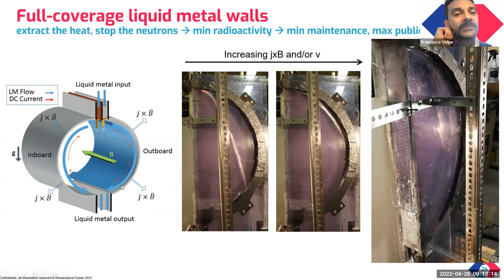So it's tens of kiloamps versus a few kiloamps. These are a rigid, very high current filament attracting a deformable current filament, but carrying a much lower current, orders of magnitude lower. And as we know, currents flowing in the same direction attract each other. The thing here is that you have these rigid HTS coils on the outside, which are attracting the deformable current-carrying medium, namely the liquid metal. But I wanted to emphasize this difference in order of magnitude.